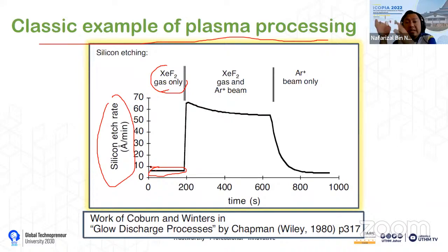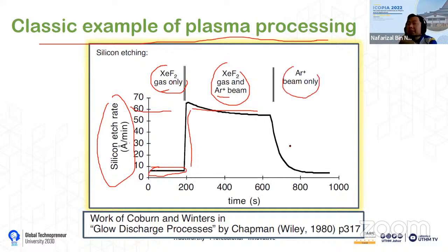Etching is a process of removing the silicon, one of the important processes for IC fabrication. If we combine XeF2 with the argon ion, you can see the silicon etching rate increase very rapidly to more than 60 Angstrom per minute. And then when they use argon beam only, it reduces back. This shows that the chemical and the plasma process here is very crucial in order to use it for microelectronic fabrication. So we can use it for silicon etching quite fast.